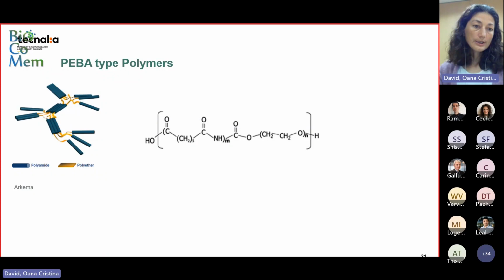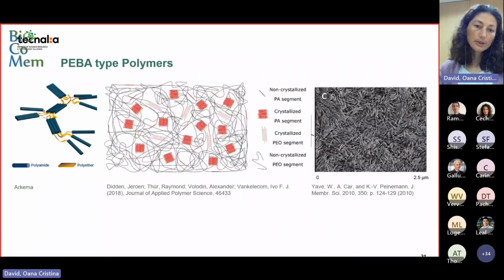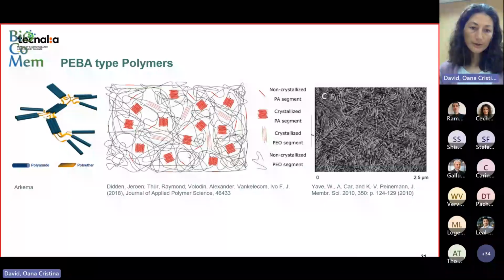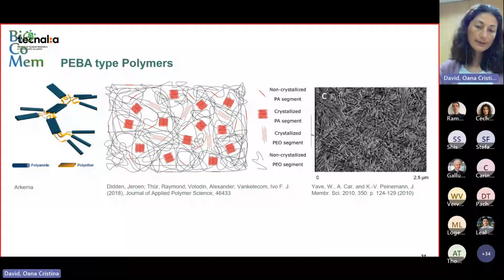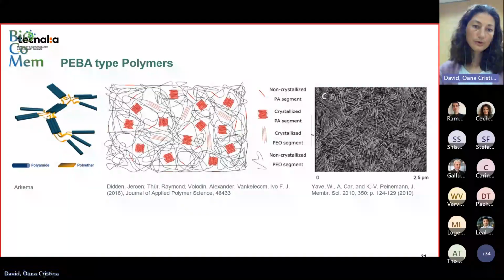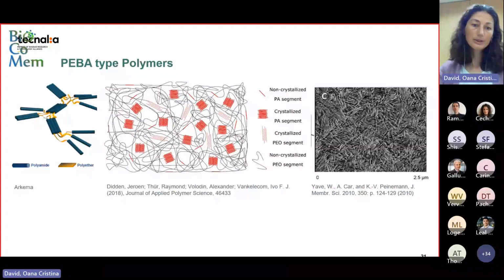So, speaking about PEBA type polymers, as I said, they are block copolymers. They have a few repeating units of each polymer, not many, like 5. And because of that, you can achieve a very unique structure. You can have the rubbery polyether oxide, very amorphous, and it's stabilized mechanically by a few units, like phases, these fibers of polyamide blocks, which are more rigid. So this composite structure is mechanically very stable, and it allows the polyether oxide phase to be in a rubbery state, which for carbon dioxide separation from nitrogen is highly important.